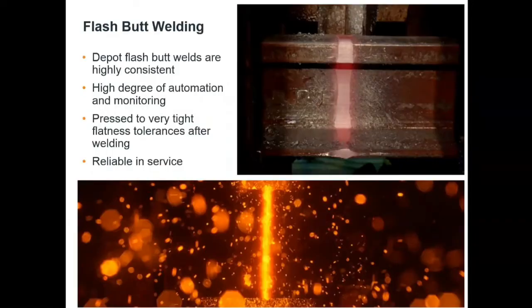Flash butt welding is the most reliable weld joint you can have in the railway, particularly depot flash butt welding. You do get mobile flash butt welders, but the depot flash butt welding is a highly automated process. We have one here in Scunthorpe, and we take two 108-meter rails and weld them together into a 216-meter string before dispatching them to Network Rail for re-railing activities within the network here. So we're quite familiar with this process because we do operate it.